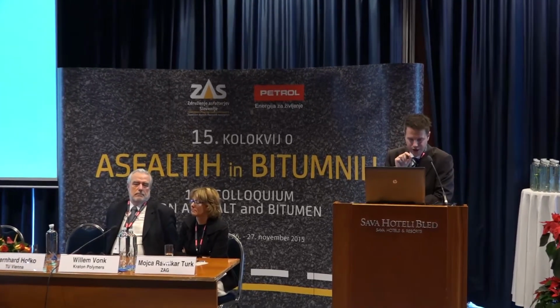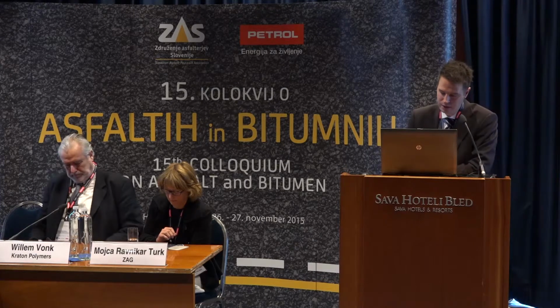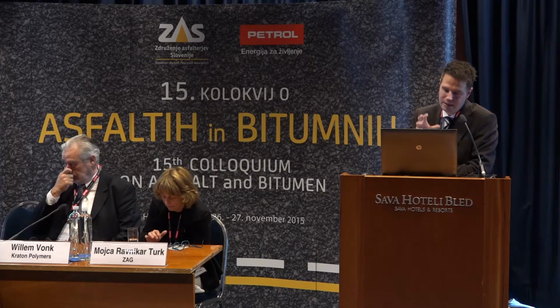When we look at bitumen microstructure and zoom out on a detail that you see in this picture, we see that we can distinguish different phases and that we can connect these phases with some chemical families. So we have these centers, the Bs, also called micelle centers, that we think are made up mainly of asphaltenes, so very highly polar material. Then we have the matrix, the continuous matrix around it, also called the maltene phase. And if you take a look at the diagram to the right, it's a qualitative diagram, but still, you can see that we have